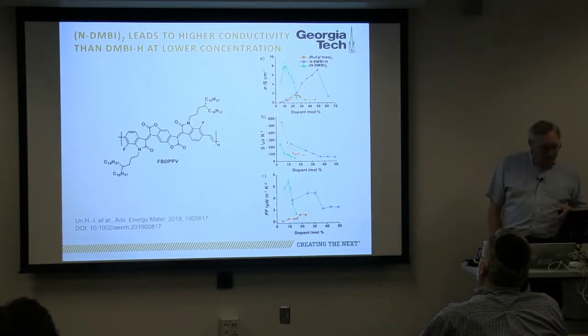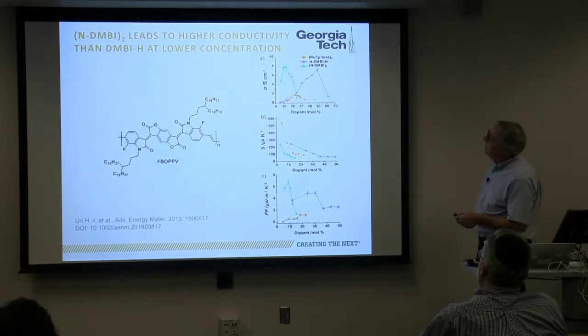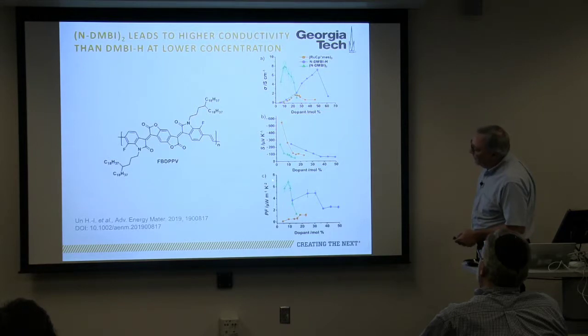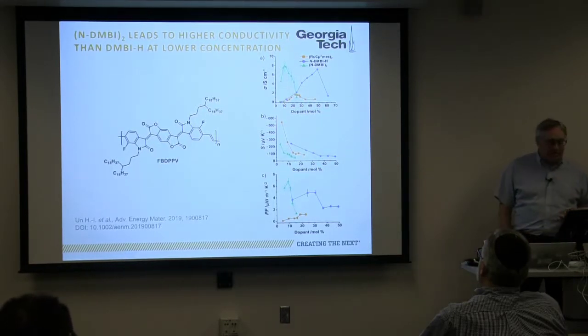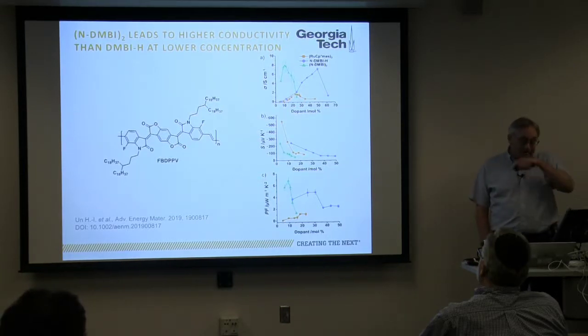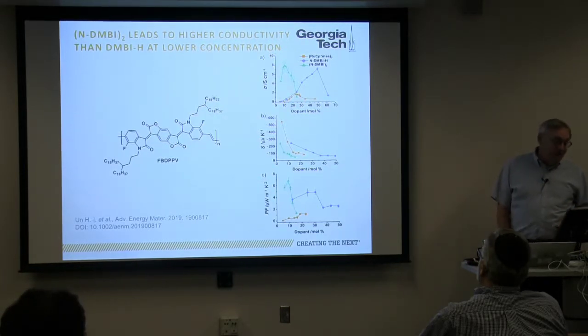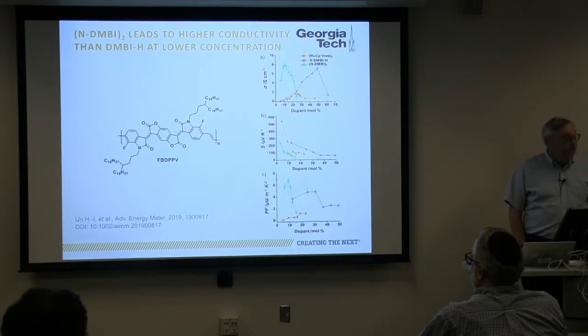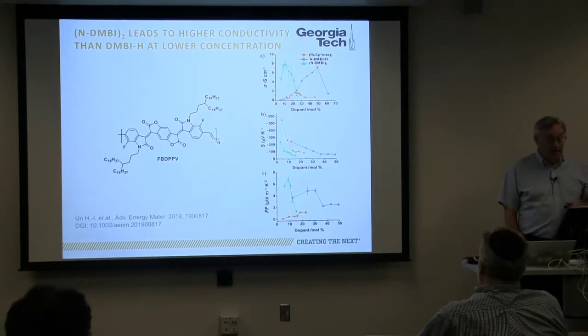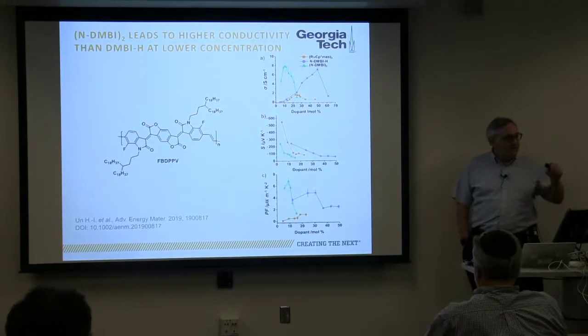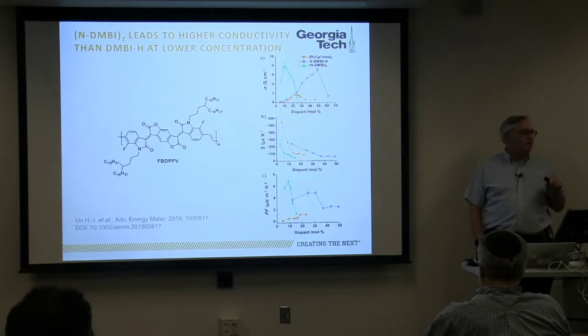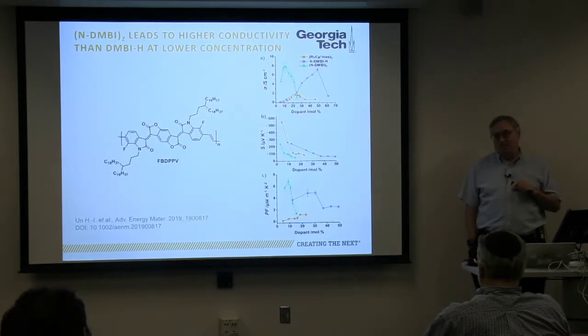And so now with these dopants, what we can do is dope materials and get up to about 8 Siemens per centimeter, and also very high, or reasonably high for n-doped polymers, power factors for thermoelectrics. What I hope to be able to talk about within a few months is a paper that we're working on now with this group in China, Jian Pei, who developed these polymers, where they're now seeing n-channel conductivities on the order of 90 Siemens per centimeter.